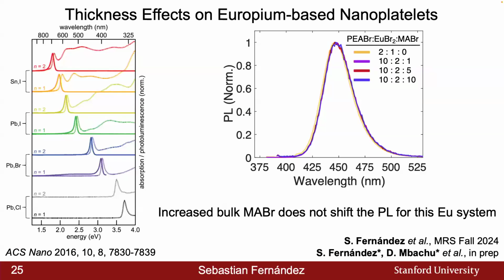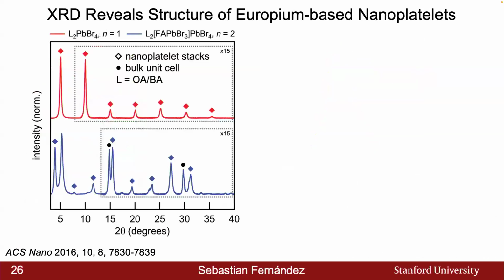Curious to understand why, we then conducted X-ray diffraction, or XRD, measurements as well. From the previous study, this is a typical XRD scan of a 2D perovskite, which has a periodic nature, and the diffraction peaks are aligned with the 00L lattice planes within the structure itself. For the N=2 nanoplatelets, we can see a slight distortion within that 2D structure. Within these black circles, we can see some peaks that are reminiscent of the unit cell that we would be creating within these nanoplatelets. The ligand species here is octylammonium and butylammonium.